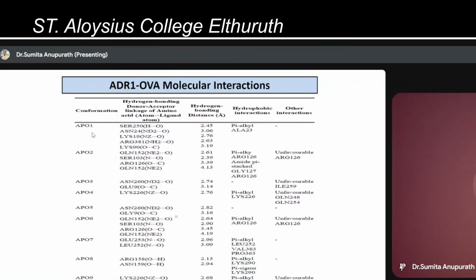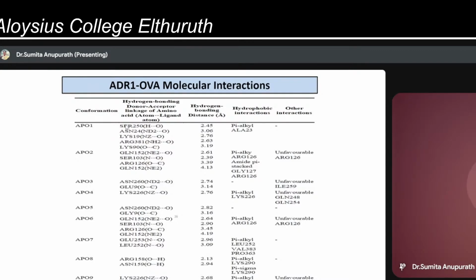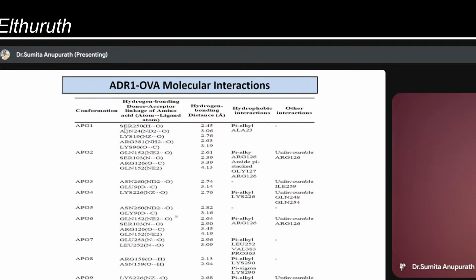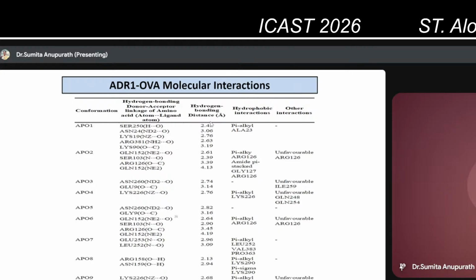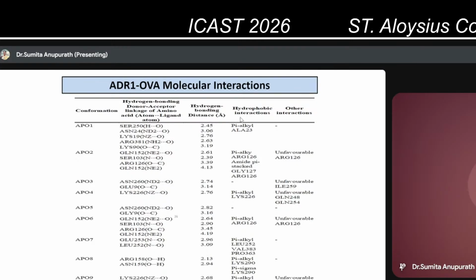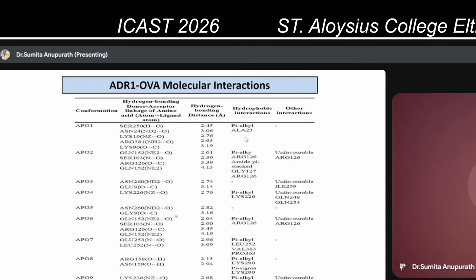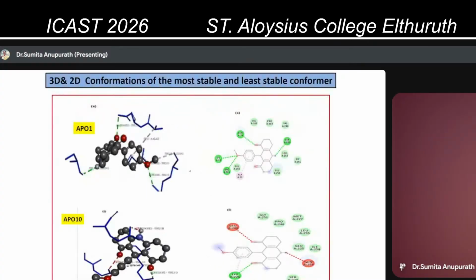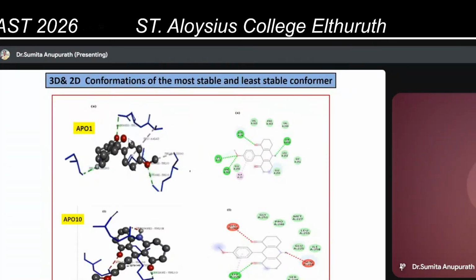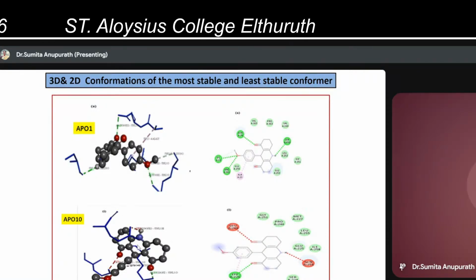This is the ADR1-ovalbumin molecular interactions. We can see that each conformer generated interacted with various amino acid residues present in the ovalbumin. And it's not that the dye will interact with only one specific amino acid moiety. No, it interacts with the various amino acid moieties available to it. And we were also able to find various hydrophobic interactions present apart from the hydrogen bonding interactions. These are the 3D and 2D conformations of the most stable and the least stable conformer.